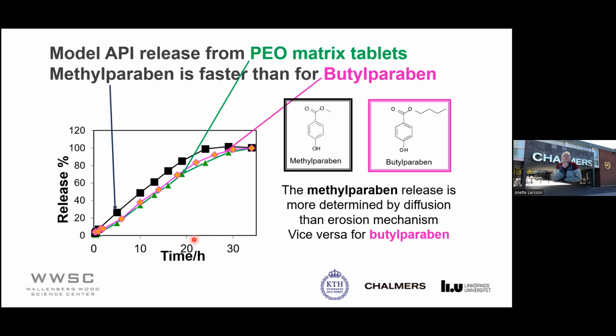I should say something also about the drug release rates. So here's another polymer matrix, that is PEO, the green one here. So that is a synthetic polymer. And here are just 2 model drugs. The butylparaben has low solubility, and therefore it is erosion controlled. So it is released at a similar rate as the polymer. So the dominating mechanism behind the release is erosion, whereas the methylparaben has high solubility, and therefore it has a higher influence of diffusion compared to the butylparaben. So even if everything else is exactly the same, we get 2 different release curves here.